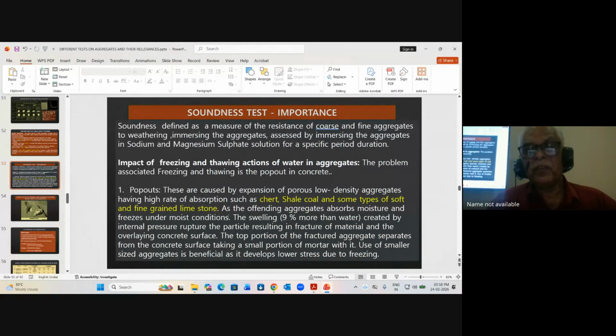Very important: the offending aggregate absorbs moisture and freezes. What happens is these aggregates absorb moisture, and when it freezes, it exerts swelling pressure, more than 9% more than water pressure. That much swelling pressure causes the aggregate to start breaking, so the top portion of the aggregate fractures and separates from the concrete surface.